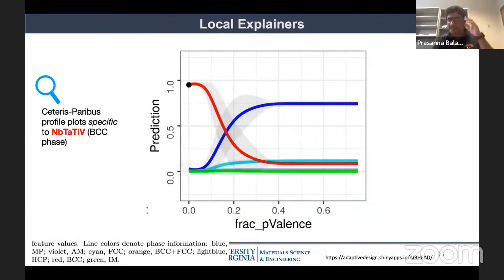So I'll explain this in this example here. I've taken one example called fractional p valence, and I'm changing it over a normalized value from 0 to 1, right? And the different colors indicate the different phases this particular alloy can form. Red is BCC, cyan is FCC, blue is a mixed phase, which means it has precipitates and so on. So what this plot tells you is that even though niobium, tantalum, titanium, vanadium is a BCC, because it has zero p electrons in the composition, right? So that's why it's zero here.